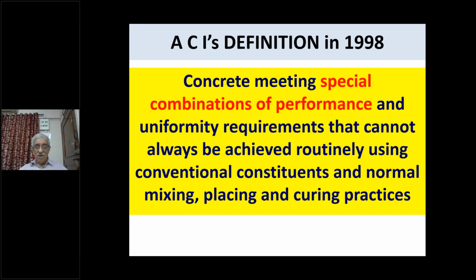Mind you, what is important now, we do several steps while making concrete. So, of course, proportioning of the aggregates and all material is important. Normal mixers may not work. You have to have high performance mixers like the ones we get in the batching and mixing plant of the ready mix concrete. Placing of the concrete has to be done correctly, because if you segregate the mix, you can't get dense concrete. And last but not the least, curing cannot be neglected right from the beginning. I will come to that in the last part of my lecture.